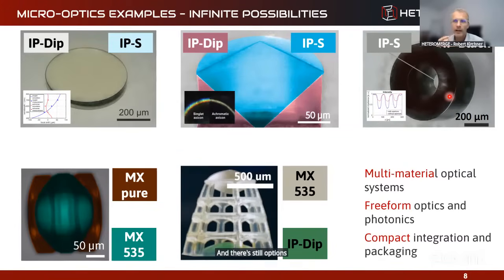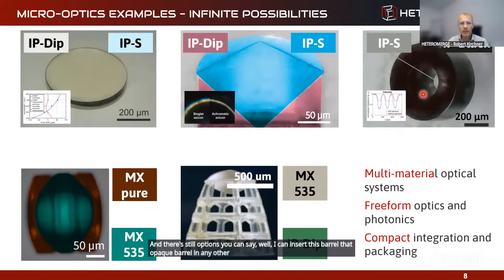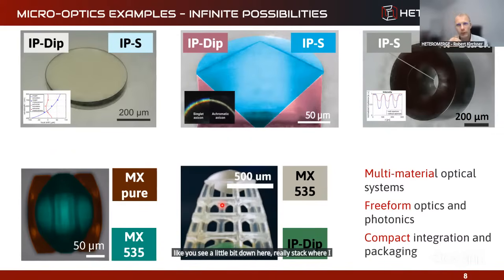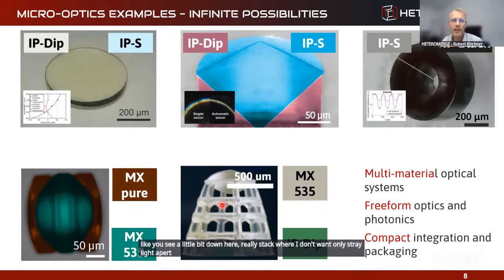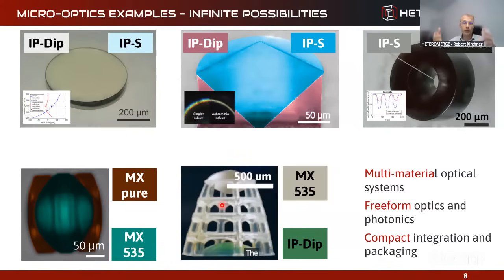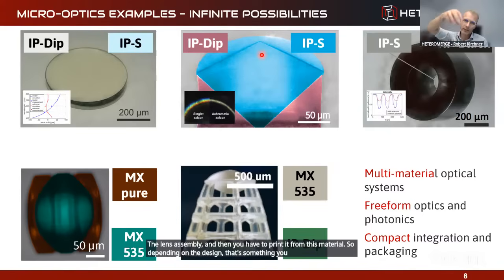And there's still options. You can say, well, I can insert this barrel, that opaque barrel, in any other way. But imagine you're really talking about a setup of lenses, like you see a little bit down here, really stacked, where you don't want only stray light apertures, where you also want the imaging apertures integrated. And there's no way you can put that at the end. You have to put this at a certain imaging plane in between the lens assembly, and then you have to print it from this material. So depending on the design, that's something you can really insert in your print. You print materials, you swap for a black material, insert the black material, and you continue printing.